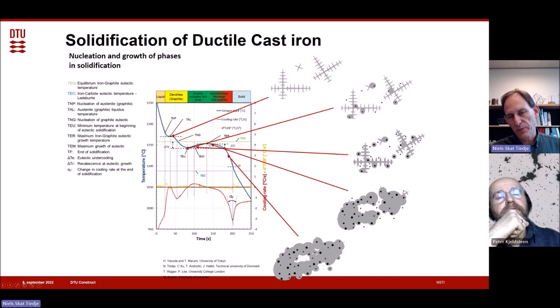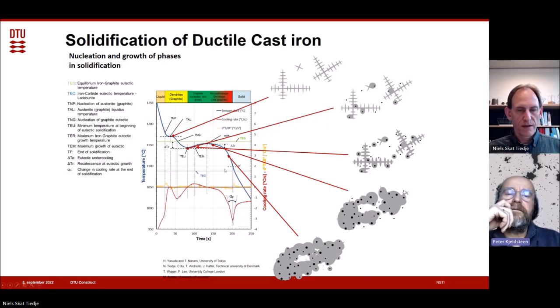Temperature increases. There's a peak. At the end, as you can see, there's so little liquid, it cannot generate heat. But we're still extracting heat, so the temperature drops. So it's this balance between extraction of energy and formation of energy in the process. So the undercooling to form the graphite is also controlled.